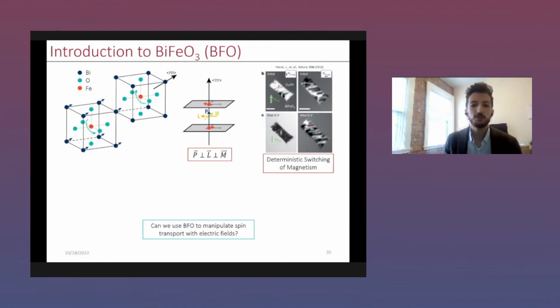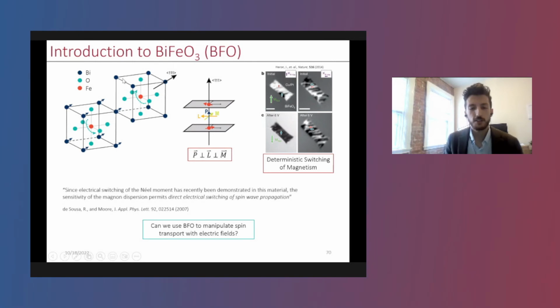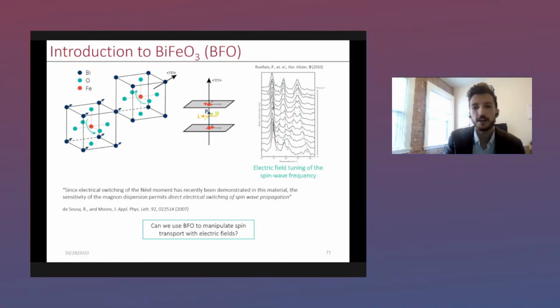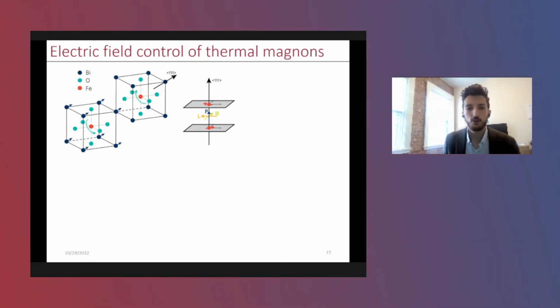And so, can we use bismuth ferrite to manipulate spin transport using electric fields? Well, this is actually a question that's been brought up for over a decade. Joel Moore and Souza both predicted that this would be the case in bismuth ferrite, and even over a decade ago, there's been some work on manipulating spin wave frequency in bismuth ferrite using electric fields. But here we're more interested in actually using electric fields to control propagation. And so how we do this is we grow this material in thin film form.